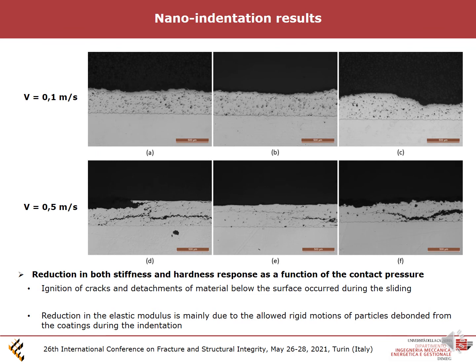This phenomenon can be explained taking into account that the trend observed for stiffness data at low speed can be related to the closure of subsuperficial defects below the worn surface, whereas regarding the experiments carried out in high-speed condition, the observed reduction in the hardness values along the thickness can be related to the ignition of cracks and detachment of materials below the surface occurred during the slide, as shown in the images presented in this slide.